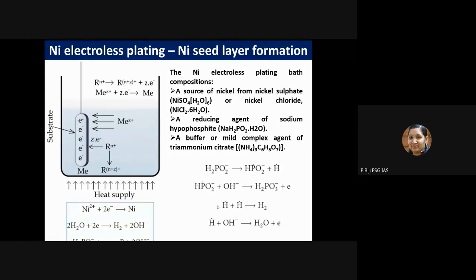It's electrochemistry. There are oxidation and reduction reactions, and the hypophosphite dissociates into hydrogen radicals, which will react with the OH minus. There will also be hydrogen evolution occurring, because these hydrogen radicals will combine to form hydrogen. So during these reactions, hydrogen evolution also will be occurring.